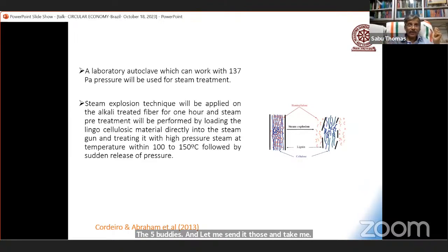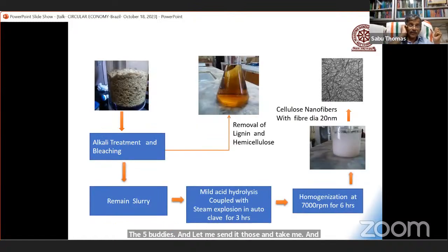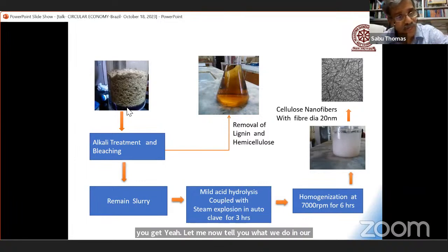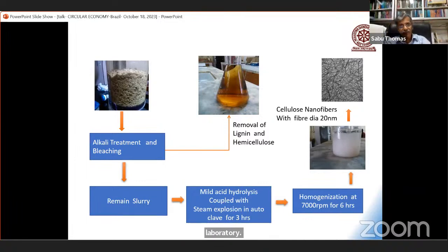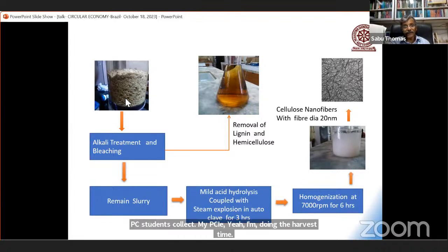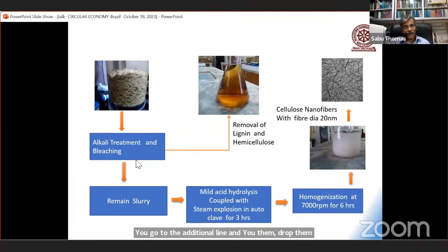and you get nanofibers. Let me now tell you what we do in our laboratory. My PhD students collect the waste from the harvest time. We go to the agricultural land and collect all. We clean them and chop them into smaller lengths. We do initial alkali treatments. Then we get a slurry. Then we go for acid hydrolysis, coupled to the steam explosion process, for 3 hours.